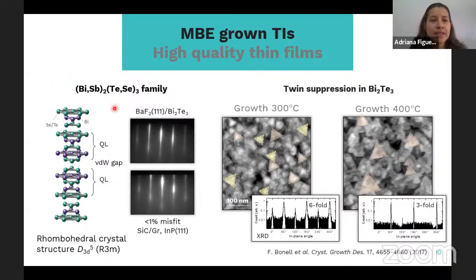So this family of TIs has a layered crystal structure. It's rhombohedral of this space group. And what we call the basic unit is the quintuple layer, because it comprises five layers: one layer of tellurium or selenium, then one layer of bismuth or antimony, another chalcogen, then bismuth or antimony, and then it finalizes with another chalcogen layer. And then these quintuple layer units are bound to the other quintuple layers by van der Waals forces.